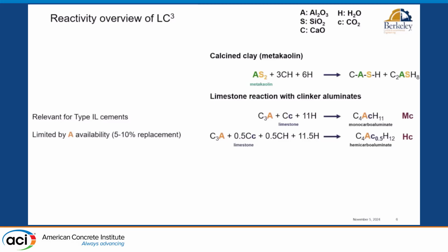But in type 1L cements, and this is what makes carboaluminates not exclusive to LC3, we have a reaction between the alumina from C3A in type 1L and the calcium carbonate and some calcium hydroxide to form hemi and monocarboaluminates, which are our carboaluminates as a group. These belong to the AFM family of phases, and what's happening here is that, in essence, when you have carbonate in the system, the thermodynamic stability moves from monosulfate, which is what would form in a normal cement, to mono and hemi-carboaluminate. In reality, at least in Europe, there is no more OPC without at least 5% calcium carbonate, because I don't know if you're aware, but producers in Europe are allowed to put up to 5% calcite without declaring it. So in a sense, monosulfate is a myth of the past, and the AFM phase that you find in all cements nowadays is hemi and monocarboaluminate, because you have that carbonate component in the system.